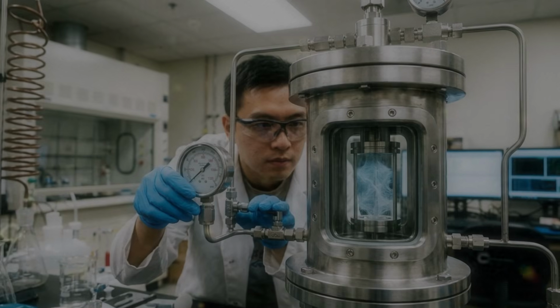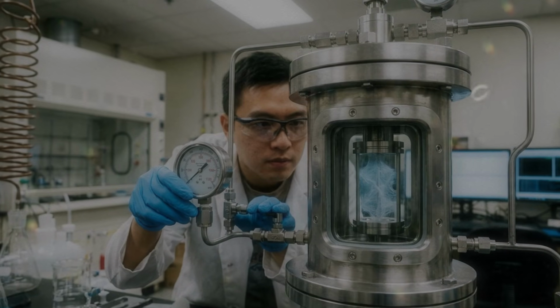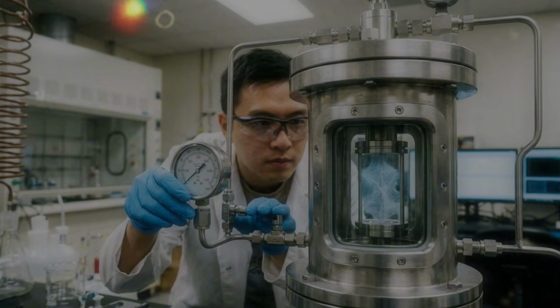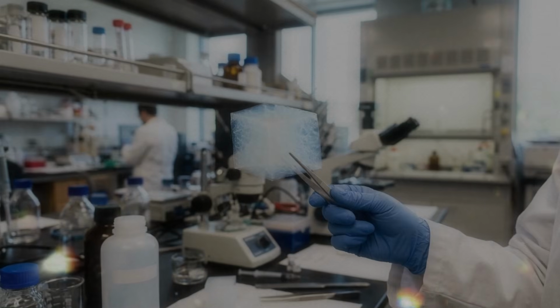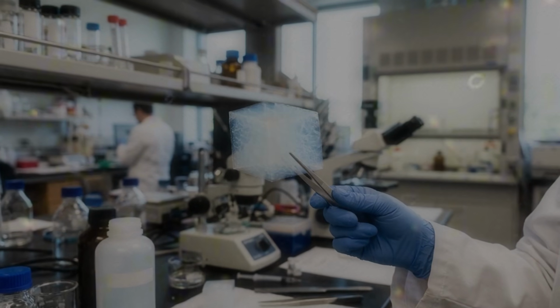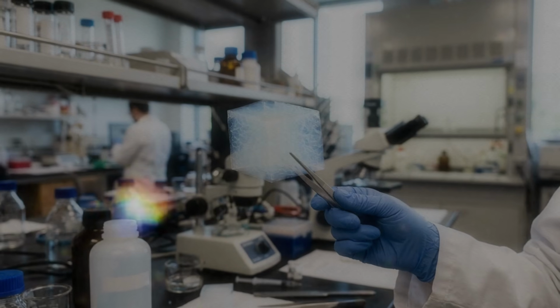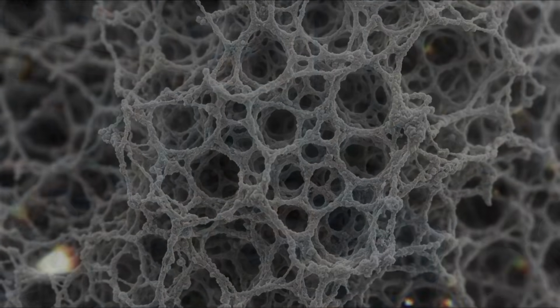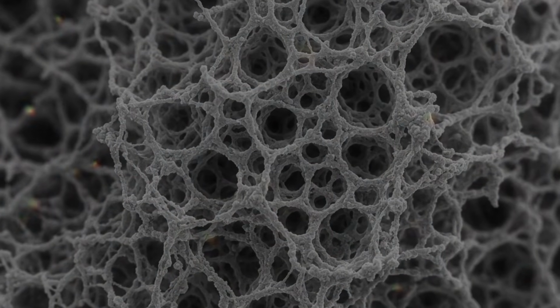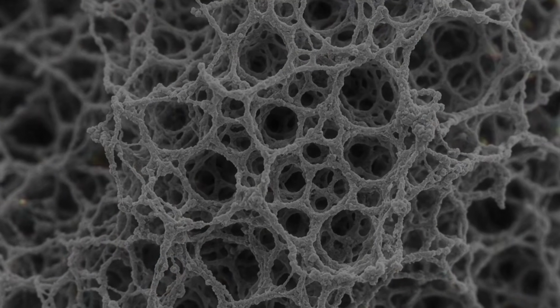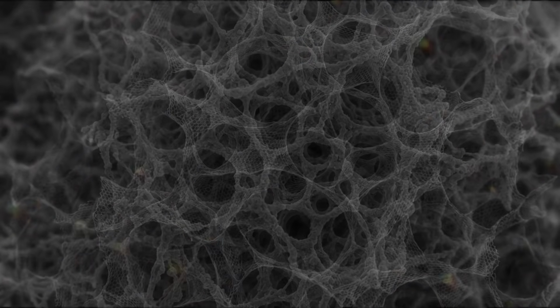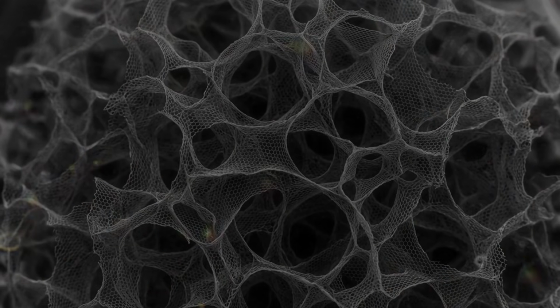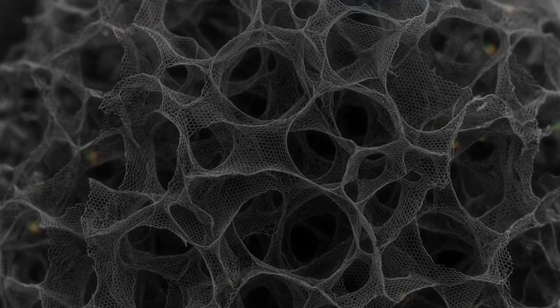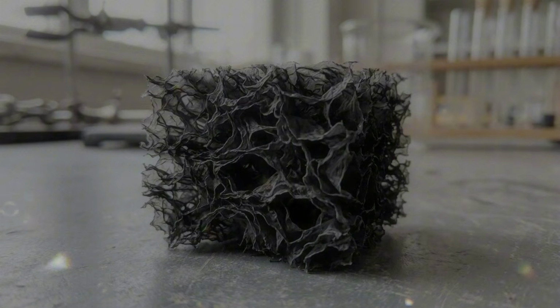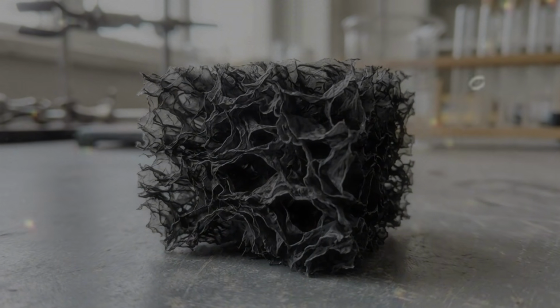In aerographene, thin carbon walls can be arranged so the object bends, springs back, absorbs vibration, or changes its electrical behavior under pressure. This design freedom makes the material more than a competition for the lowest density. A record number may introduce the public to aerographene, but engineers are more interested in controlled performance. A slightly heavier aerogel that works for thousands of compression cycles may be more useful than a lighter one that collapses when removed from its mould.